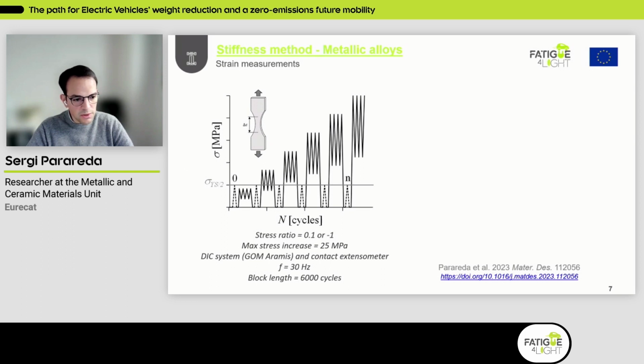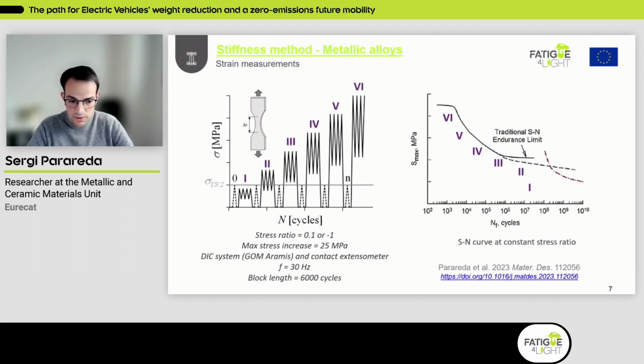And the new point of this method is to measure, as mentioned, the elastic response of the specimen between each one of these fatigue blocks. This will describe the evolution of the fatigue damage in these tests. And at the end, what we are doing is covering the whole SN curve by starting at very, very low stress and finishing the test when the specimen fails.